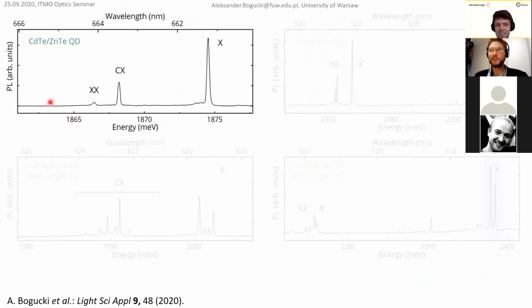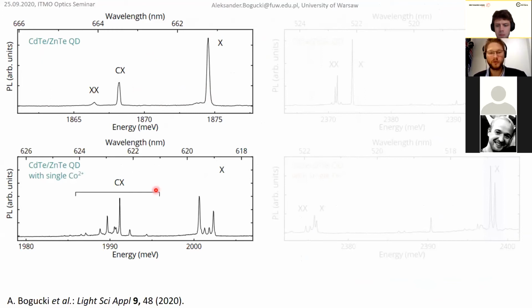So this is now our example of quantum dots. This is an example of a single cadmium telluride quantum dot without any magnetic impurity. As I mentioned before, we love magnetic impurities. So this is a single quantum dot with a single cobalt ion. As you can probably guess, it's quite difficult to find exactly such a quantum dot. You have billions of quantum dots on a sample, and you are looking only for quantum dots which have one magnetic impurity inside. And you recognize them by characteristic fingerprints, like these 4 emission lines with characteristic intensities. Which is nice, but then finding the same quantum dot again or measuring it in a different experimental setup is almost impossible. And here, because this quantum dot is in a position marked by the microlens, you can measure it easily.